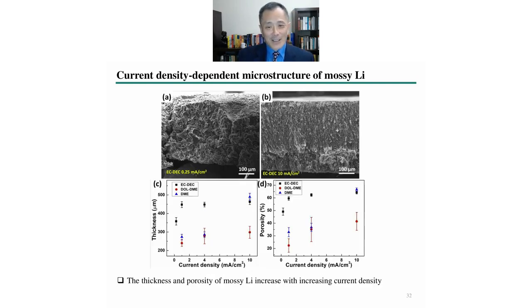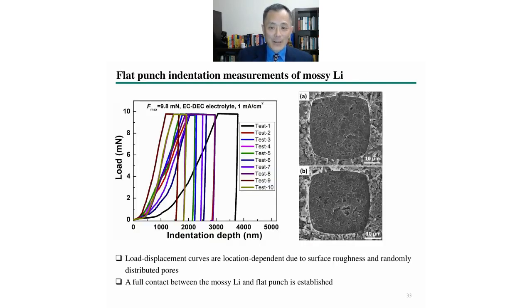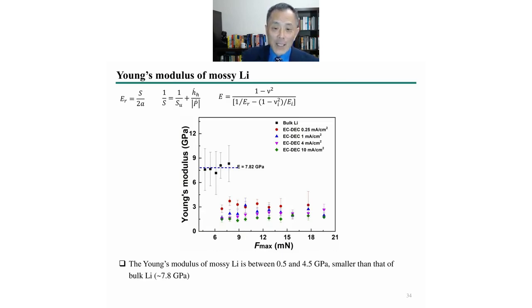Because of porosity differences, the total thickness of the lithium, of course, would also be different as a function of current density, as well as the electrolyte used. So we use this flat punch indenter to load, hold and unload. This flat punch indenter is sufficiently large to cover a large number of dendrites, so we again measure an average property of this porous or mossy lithium. From this measurement, we can obtain the modulus of mossy lithium. Unsurprisingly, the modulus of the mossy lithium is lower than that of the dense lithium foil.